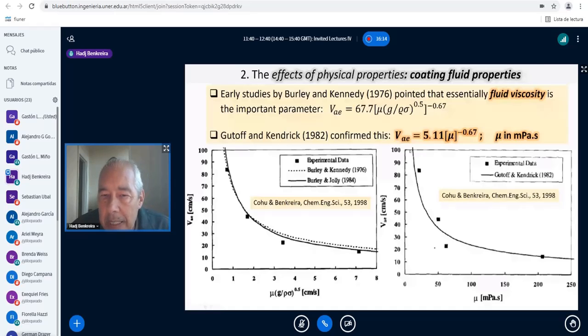So this very simple correlation is very useful to try to predict what kind of viscosity you need in order to be able to coat at a certain speed. And remember that in this equation, the viscosity is given in millipascal second. So be very careful when you use this equation.